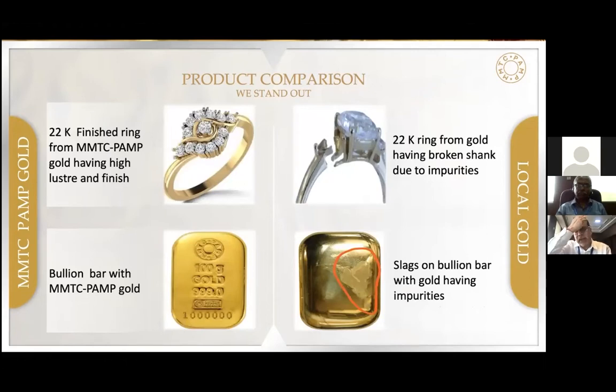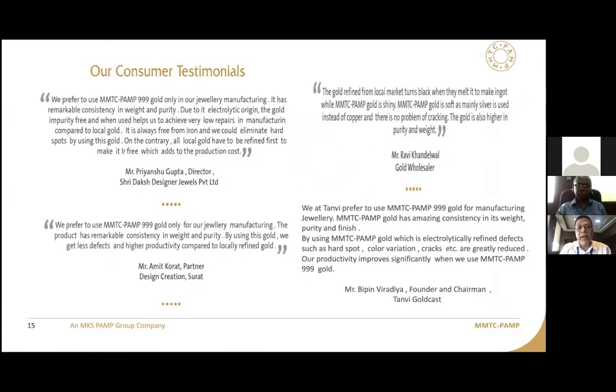And when we make the cast bars of 100 grams, we do find that there are slag inclusions coming. We did check with a few people, and they said that they do face some of these problems. Sometimes some of the manufacturers refine the gold which they receive, and then they take it to the next process.